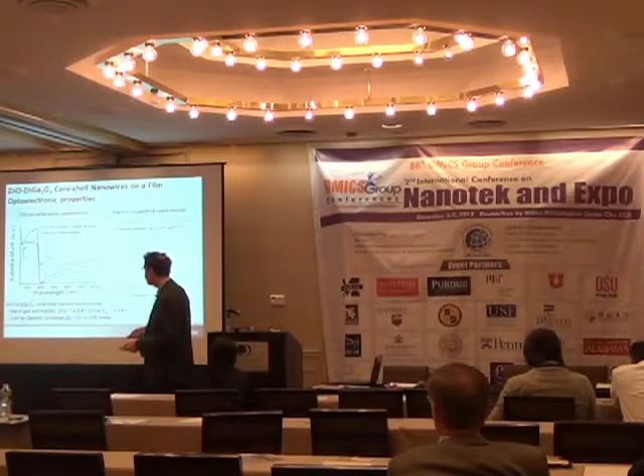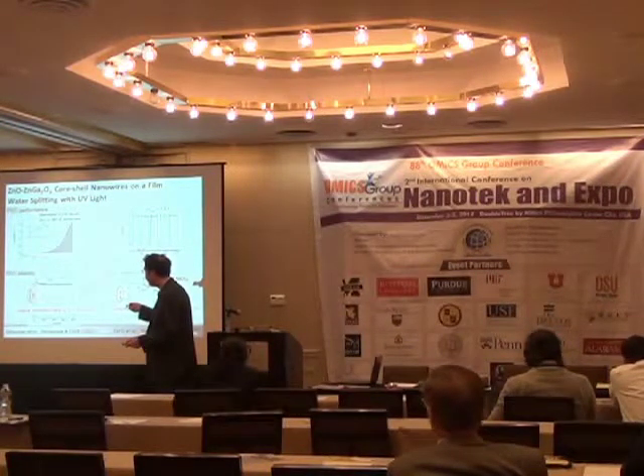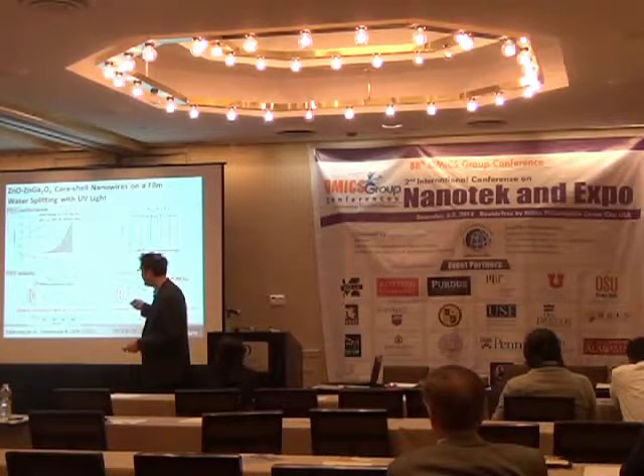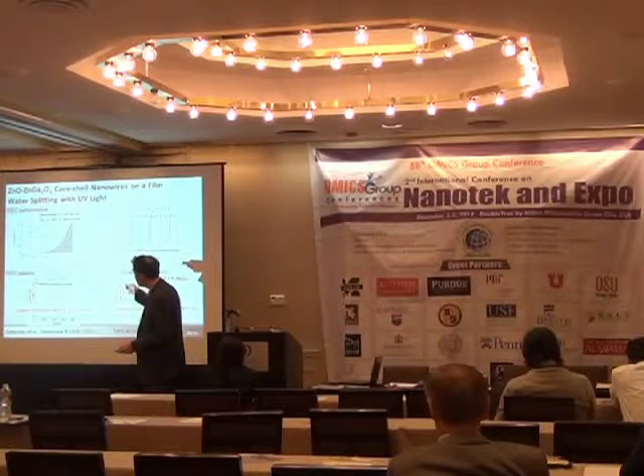Good. Okay. So this is the zinc gallium oxide absorption and the zinc oxide band edge absorption. So both are there, that's for sure. And I show you the result of water splitting here. So this is the on-off current. Zero means the dark current. So you see that the dark current is zero when we increase the voltage. This is a very important information. By increasing the voltage here, we are not changing the dark current. It means that we really are doing water splitting here and not splitting the water by just applying the voltage. Okay? So this value here is the photocurrent on illumination, and the dark current is very low here.